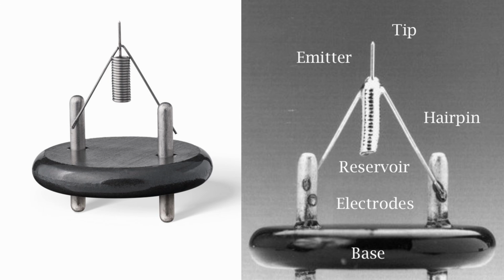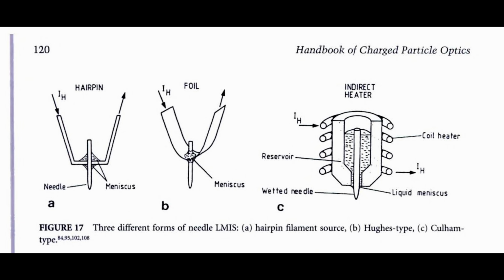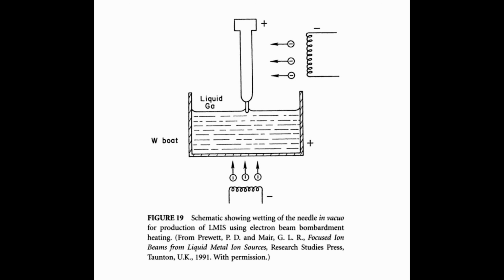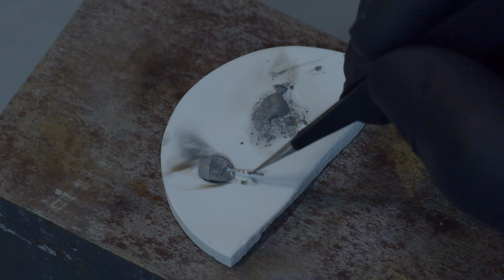Incidentally, focused ion beam microscopes use a gallium ion source with basically the same structure, a sharp tungsten tip. So how are those made, you ask? Well, the tungsten is heated to a white hot heat in ultra high vacuum and then dunked in gallium, which has also been heated and allowed to react for a while. And I don't know, that sounded like a lot of work. So how about a blowtorch instead?